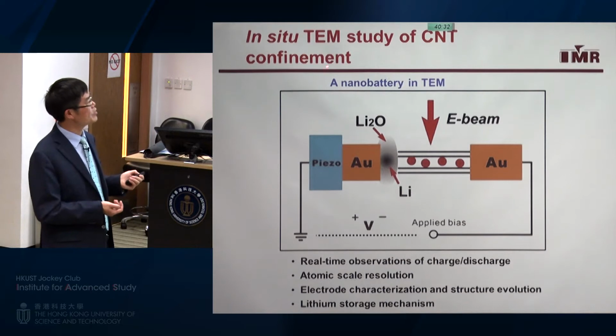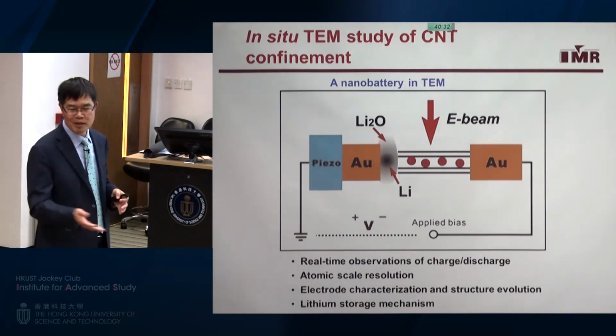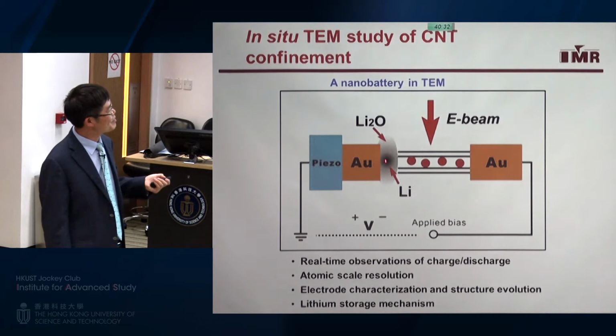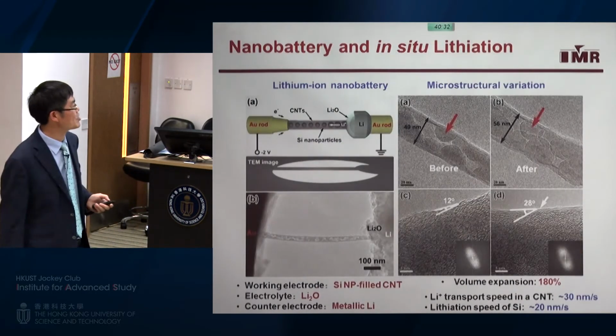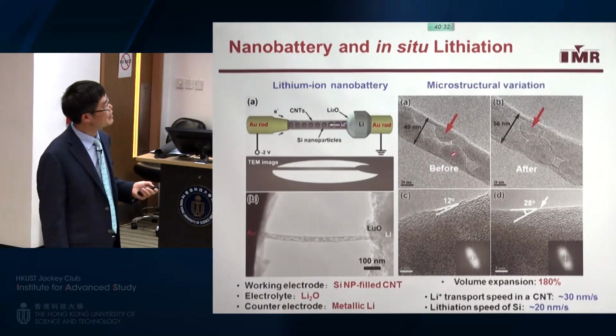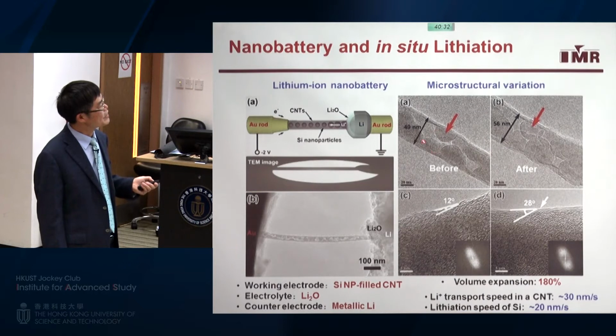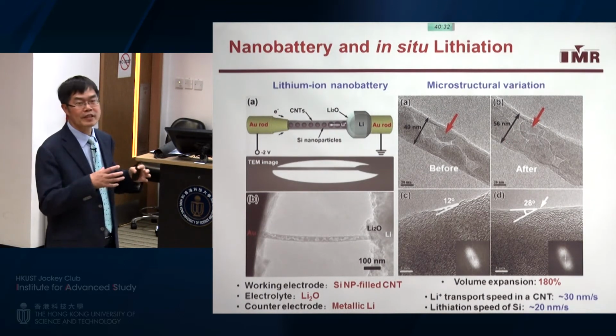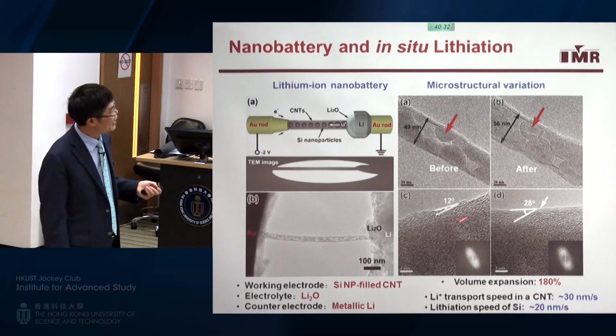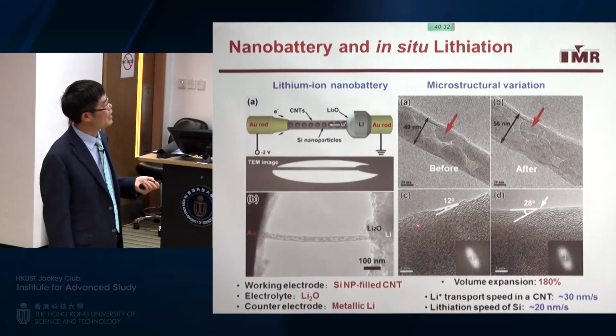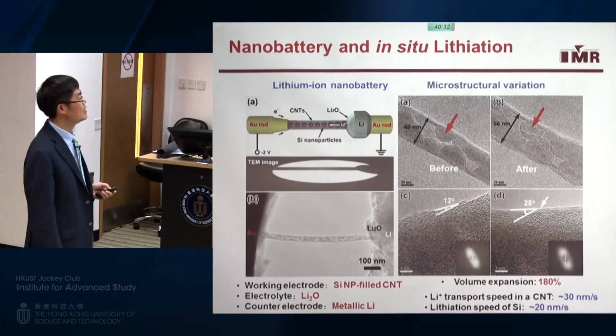So we have done some in situ TEM. This is a very simple TEM compared to Professor Wang's work. We have this electrode with some lithium on it, and then we put this silicon-filled carbon nanotube on another electrode. Then we can observe performance during charge and discharge, as I show you here. You can see after charging, the space has actually been filled because the silicon nanoparticle expanded, and even the diameter has been enlarged in some way, and it also changed the structure of the carbon wall.